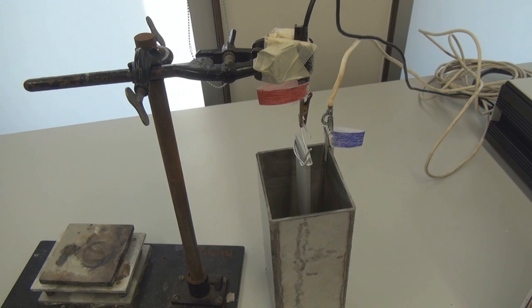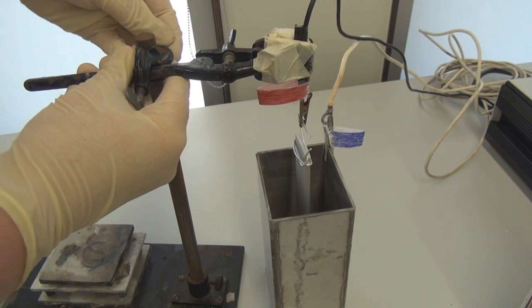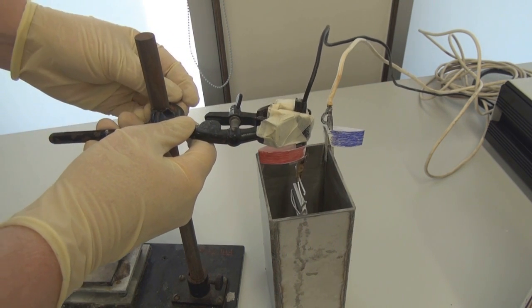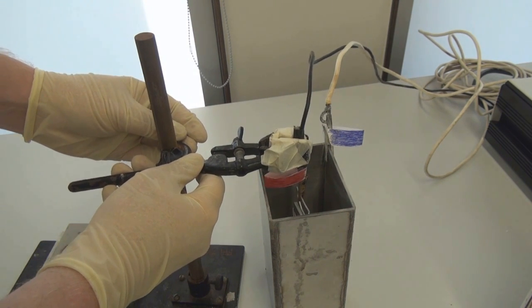In order to get a uniform oxide layer all over the anodized plate, I recommend using a stainless steel bath as cathode instead. The bath should match the size and shape of the anodizable substrates.